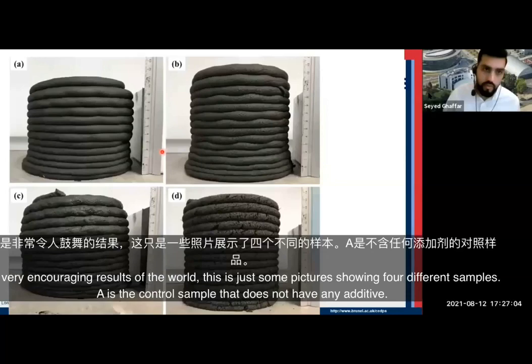We also obviously looked at the microstructure of the specimens after failure, after they were subjected to a flexural test. Again, we can explain the high flexural strength of the samples with PVA fibers by looking at the microstructure. And you can see that the cracks have been bridged by these fibers. It shows that it takes a lot more stress in order to break that sample compared to a control sample that does not contain any fibers. So these are just additional information that proves the mechanical observations.